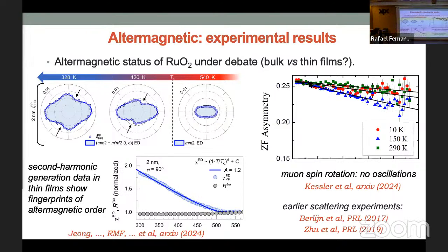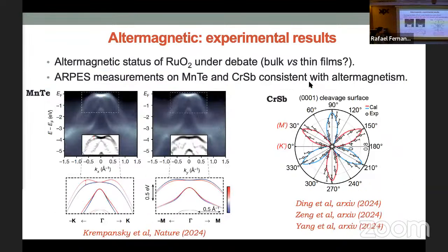Now, this is a paper from my collaborators in Minnesota, the group of Bharat Jalan. They can grow extremely thin films, 2 nanometers thick. And there, you can do second harmonic generation. Second harmonic generation is great for extracting a magnetic point group, and you can see there's a clear hint at a certain temperature, and the best fit is to a magnetic point group that is what you expect for an altermagnet. So films, bulk, thick films, thin films, there are lots of questions going on, which makes it exciting. If everybody agreed, maybe it would not be so exciting.